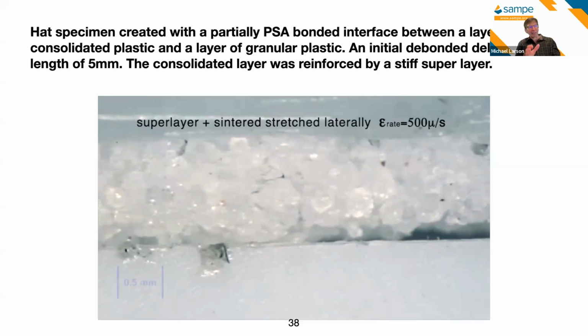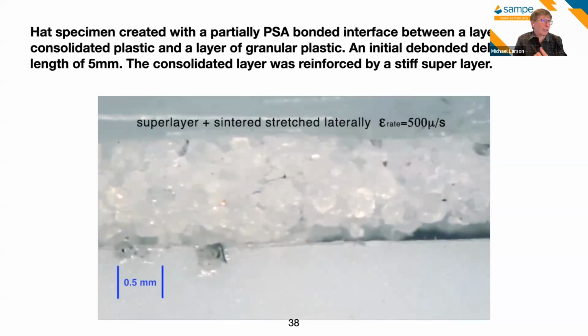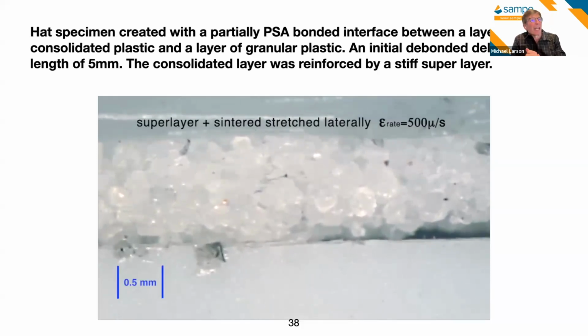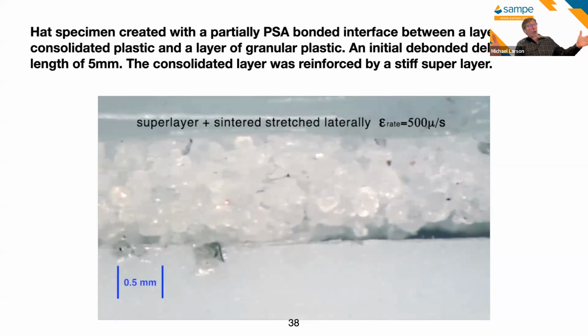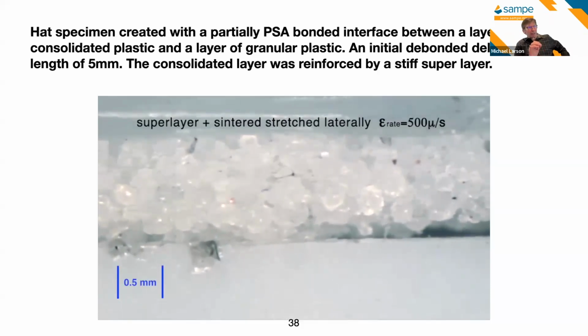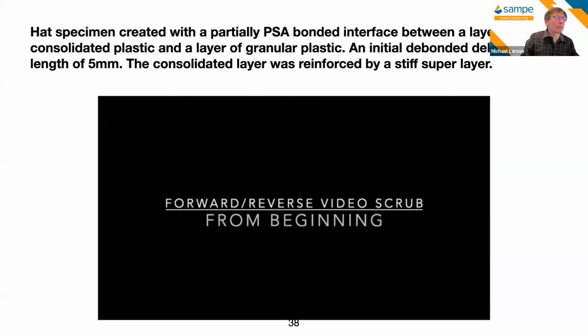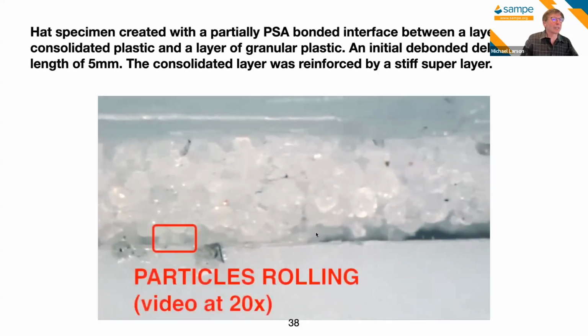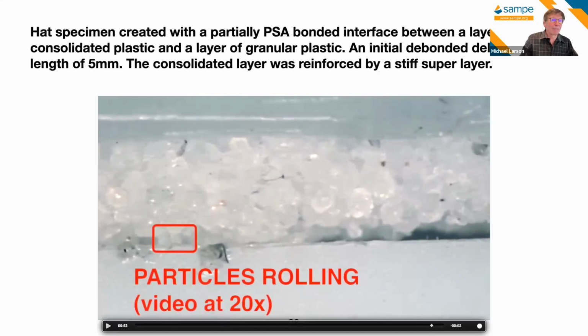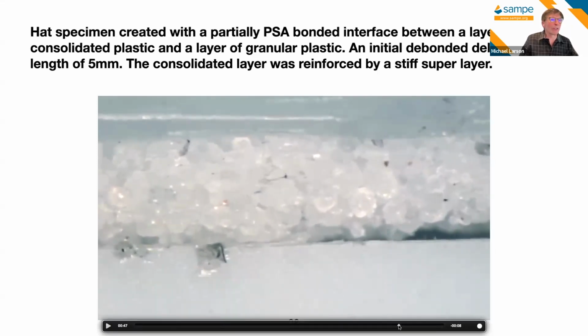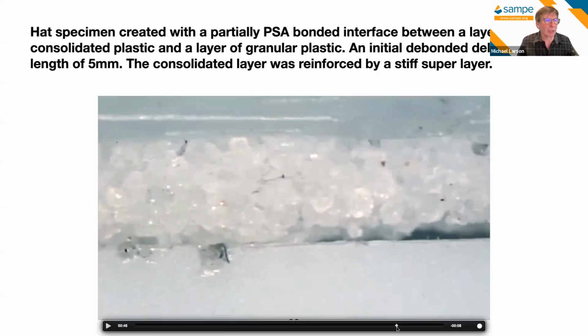So in this picture on the right, the particulate layer is not bonded to the lower substrate. On the left of that arrow, it is bonded, and the specimen is pulled apart at a rate of 500 microstrain per second. There's a little blue indicator showing these particles are about a quarter millimeter, but you couldn't really see what was going on. Can I pause this video by clicking on it? You couldn't really see what was going on in the actual video. In fact, by eye, it was hard to see that anything was moving.